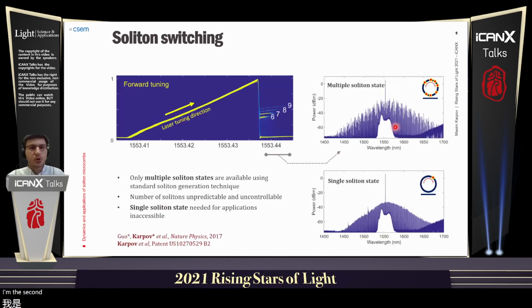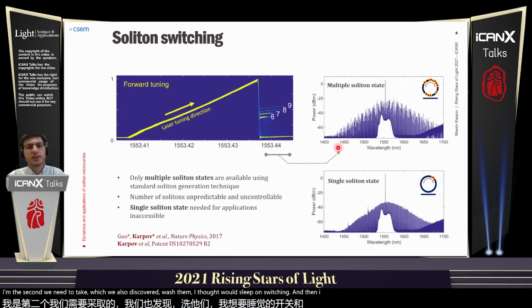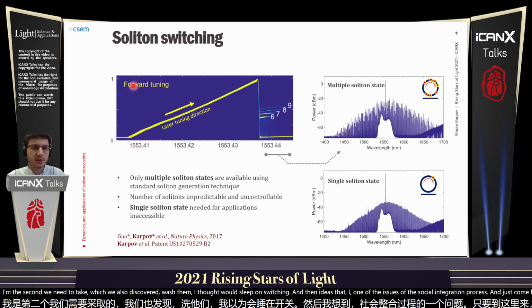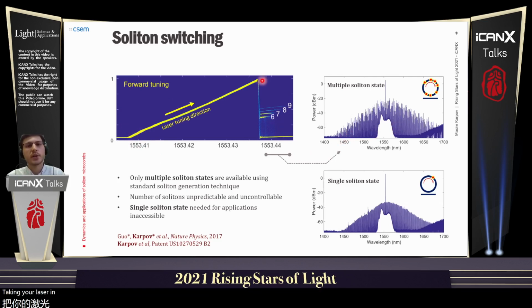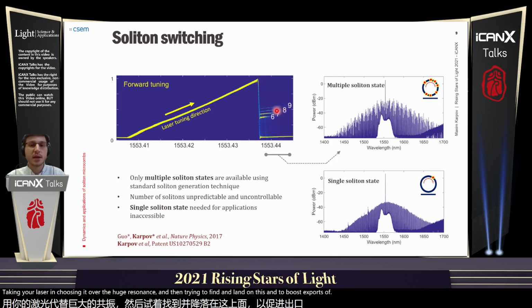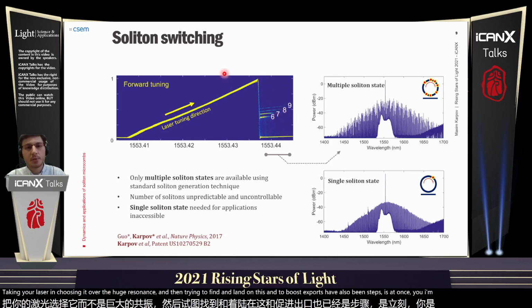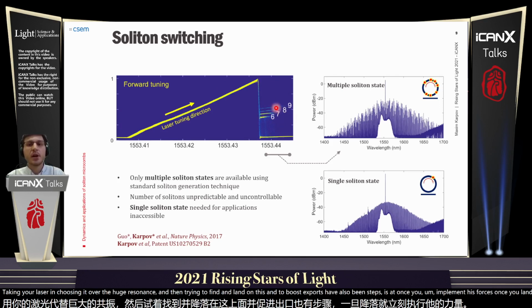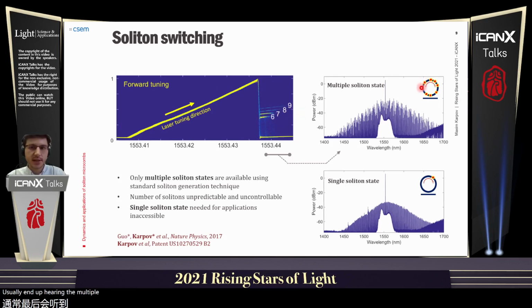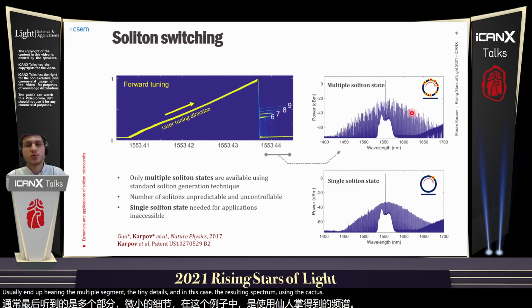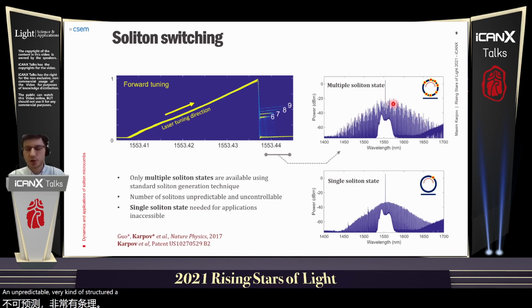The second unique effect, which we also discovered, was the so-called soliton switching. And the idea is that one of the issues of the soliton generation process, which is shown here, which consists of essentially taking the laser and tuning it over the cavity resonance and then trying to find and land on these characteristic so-called soliton steps, is that once you land on the soliton step, usually you end up having multiple solitons inside the cavity. And in this case, the resulting spectrum usually has a very unpredictable, very structured shape, which is hard to use for any applications.